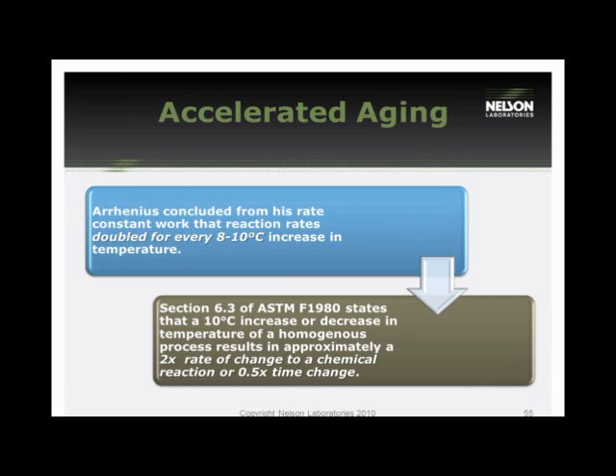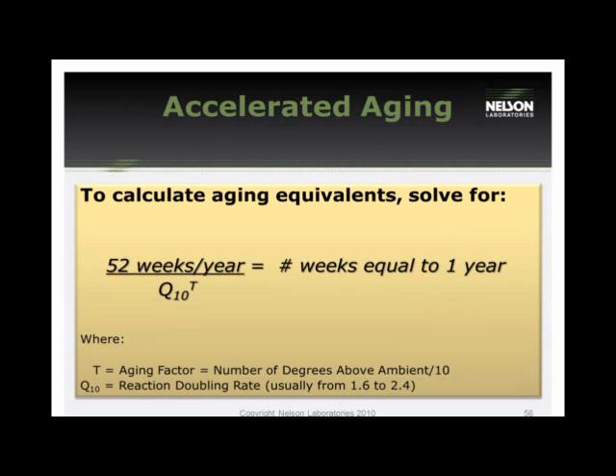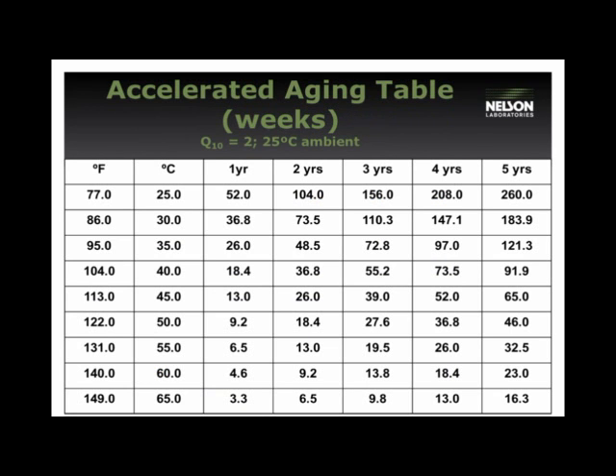The short of it is that for every 10 degrees above the ambient temperature, the reaction rate doubles. So using that formula and plugging it into this mathematical equation, you're able to determine how many weeks in an accelerated aging chamber is equivalent to a real-time one-year factor. Usually at this point, I throw out some numbers and have everybody do some equations, but for this situation, I've done it ahead of time. So an average 1 year of real-time aging is equivalent to 4.6 weeks in the chamber at 60 degrees. If you're doing it at 55, it's 6.5, and it goes up as you decrease the temperature.